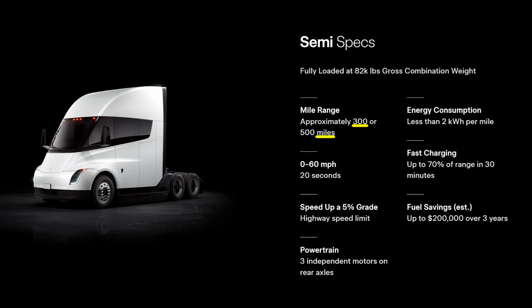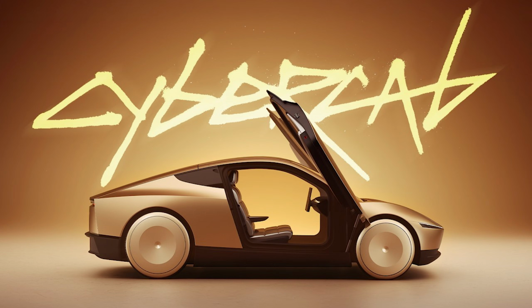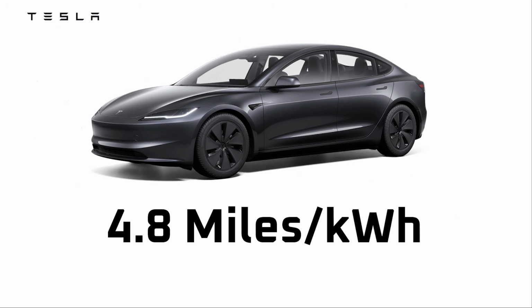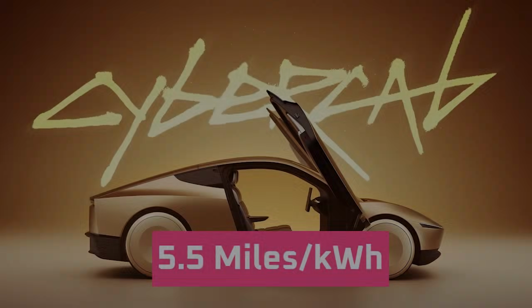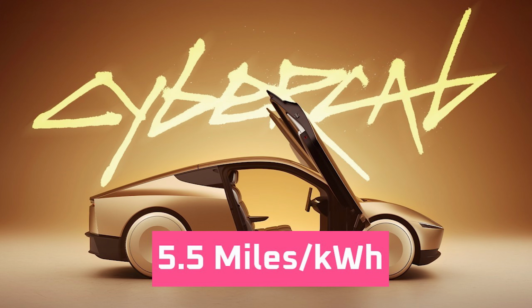Moving on to the Semi, the LFP 4680 could easily provide the 300 miles of rated range for the shorter range version. That's because the current Semi has about 500 miles of rated range. And even using the bearish 0.63 ratio above, that would mean 315 miles of rated range. Where the LFP 4680 is most viable is the Cybercab. The Model 3 has a peak energy efficiency of 4.8 miles per kilowatt hour, whereas the Cybercab is expected to have an efficiency of at least 5.5 miles per kilowatt hour, or 15% higher.